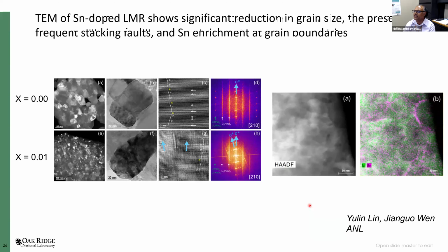And we believe that the kinetics is improved because the grain size is decreased, and something magical happens by which even with these small amounts of dopants, we are able to modify a key electrochemical property, such as the area specific impedance, which we ourselves were, well, we were pleasantly surprised that we were able to alter this. We hope that this will give us a vehicle to start looking into other dopants and seeing how we can maximize performance out of these materials.